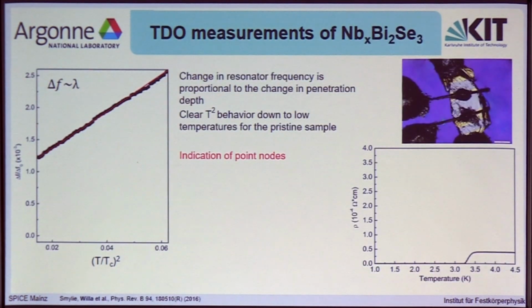But I will come to this in a moment. Let's first look at the measurements. So we've done these measurements for niobium-doped bismuth selenide. You can see here the penetration depth dependence. It is clearly a T-squared dependence. Pay attention to the axis down here. And so we could take this as an indication of point nodes.